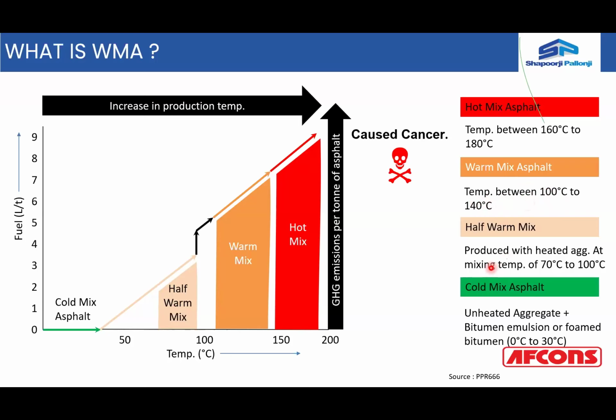When it comes to half mix, the heated aggregates at a mixing temperature of 70 to 100 degrees is what is being developed, known as half mix, or half warm mix. And of course, the unheated aggregates, when added to emulsion or foam bitumen, you call it cold mix asphalt, which is generally used for repairs and patchworks.